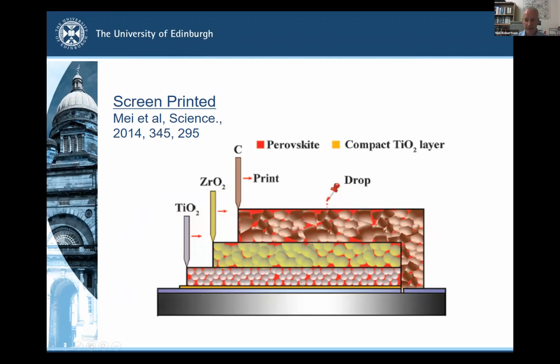So this is a side view of the cell, and in this particular implementation, all these electrode materials are fully porous. These porous electrode materials are printed first by screen printing, a methodology used to print t-shirts, so it's ultra simple and cheap. Then the perovskite absorber material is interpenetrated through all the pores of the material. Because it's contained in these nanopores of these host materials, it's protected and stabilized, and